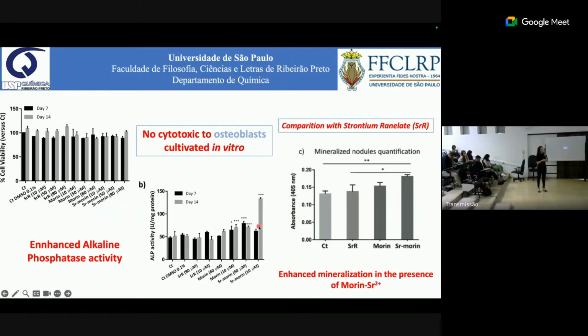We found that using the same concentration of the drug, using the same concentration of strontium ranelate, we got higher alkaline phosphatase activity for the flavonol morin complex. And if we look here at low concentration, strontium ranelate had no effect compared to the control, that were the cells cultured in the absence of these compounds. We also got higher mineralization when we used strontium morin compared to the control mineralization by the cells.